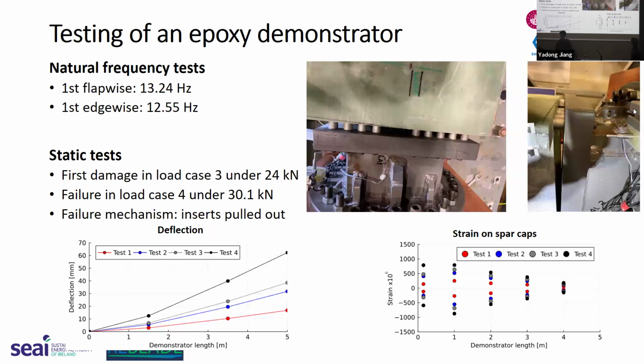First is the natural frequency in flapwise and edgewise directions. And secondly, the static test. We found the first damage in load case 3 at a load of 24 kilonewtons. We heard a sound, and there was a slight drop in the loading. Then we decided to load the demonstrator to failure in the last load case. Ultimately, in load case 4, the demonstrator failed at a load of 30 kilonewtons.